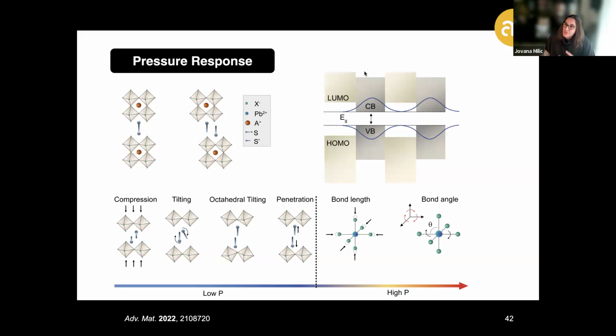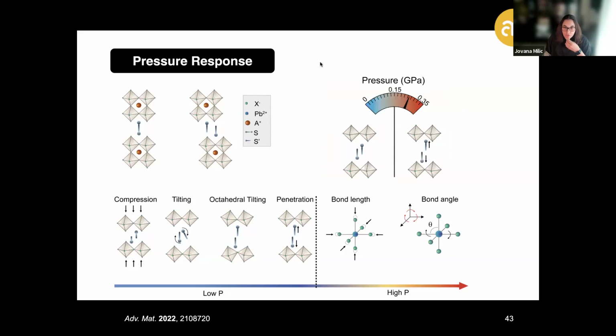Now, to assess the capacity to do this while at the same time doing it reversibly in more adaptive systems or smarter nanotechnologies, we have analyzed both Ruddlesden-Popper and Dion-Jacobson analogs or model systems to illustrate this that I would like to share briefly with you. We have also focused for this purpose on a relatively low pressure range up to around 0.15 gigapascals, which in fact corresponds to the level of strain that is more comparable to the strain that can be induced by some of these structural rearrangements within the spacer layer.